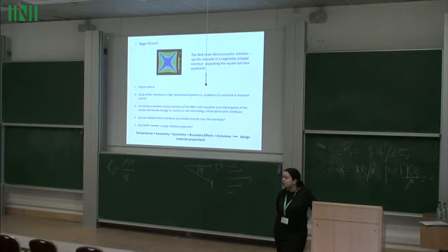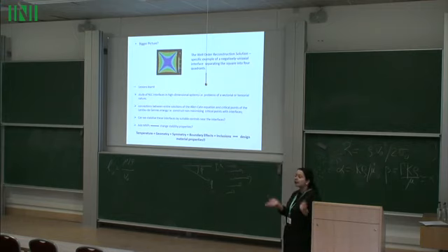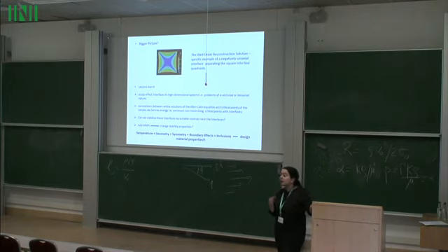So if you think of the Q tensor as being the second moment of a PDF, and then you subtract the isotropic part, which is what Professor John Ball did in his talk, you would naturally get something which is symmetric and traceless, because you want to measure the difference from an isotropic state where you don't have this orientation. So you're measuring the degree of anisotropy, the degree of orientational order. When you subtract that isotropic part, that is what gives you the traceless part. But that's a statistical mechanics approach.